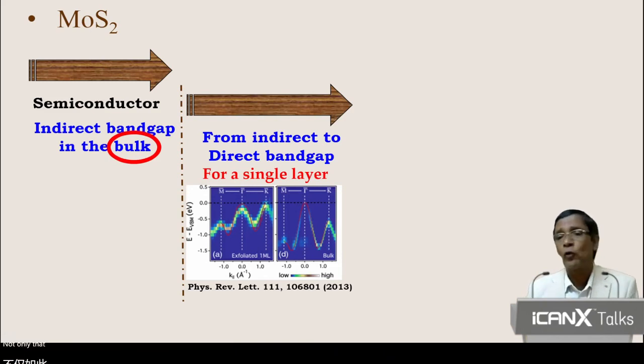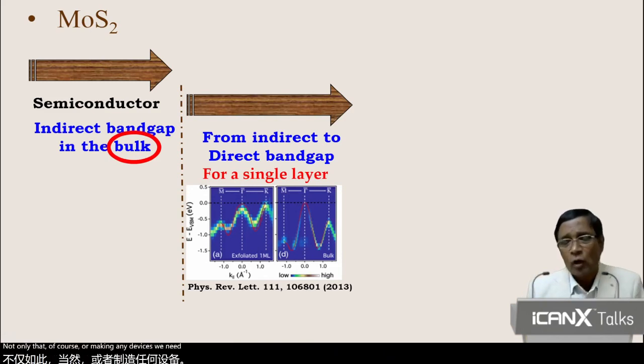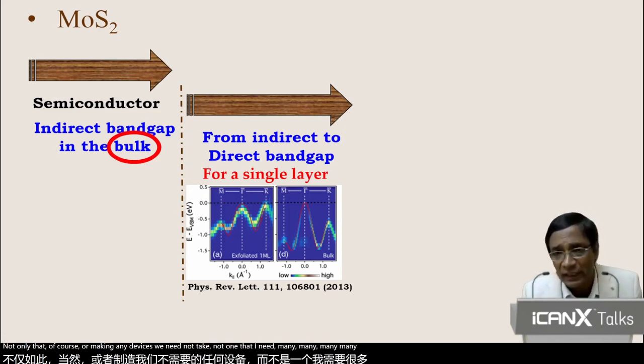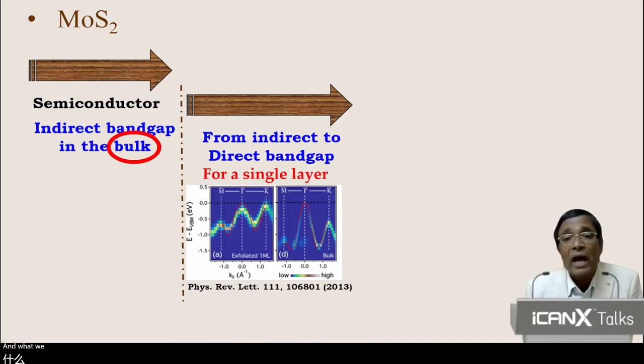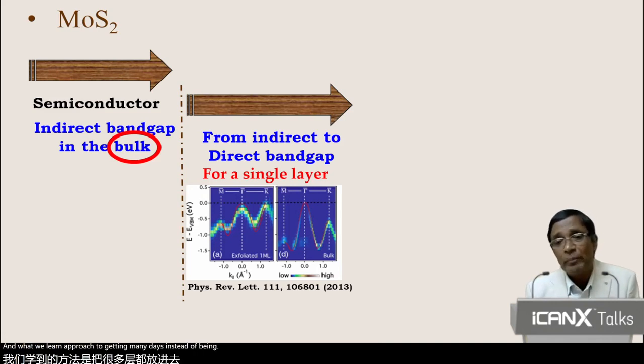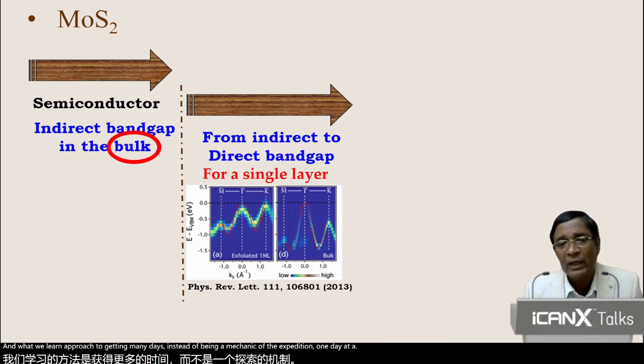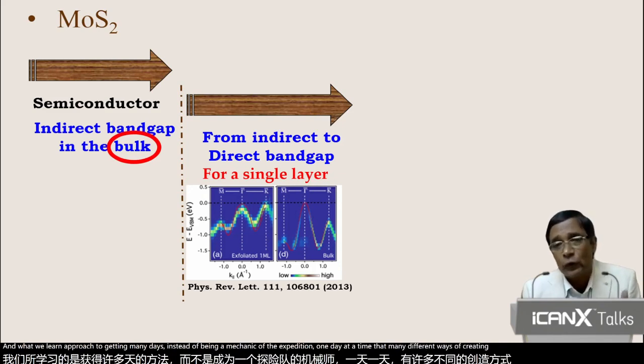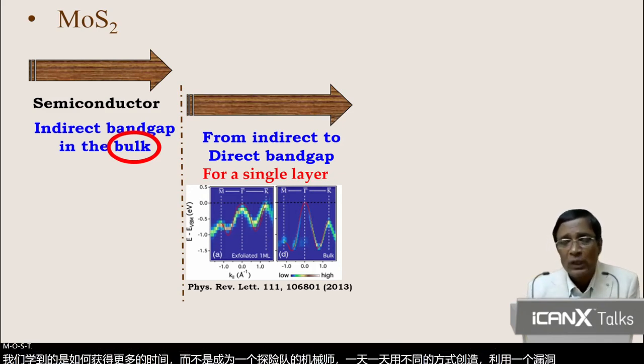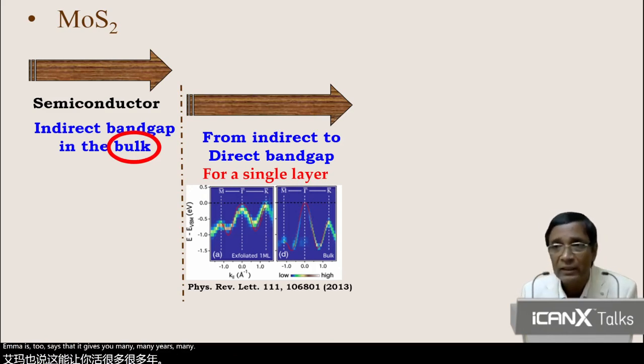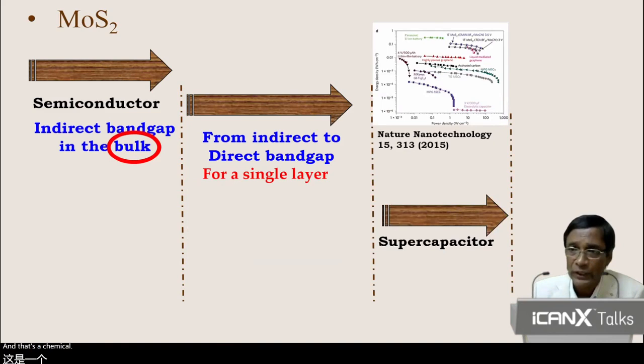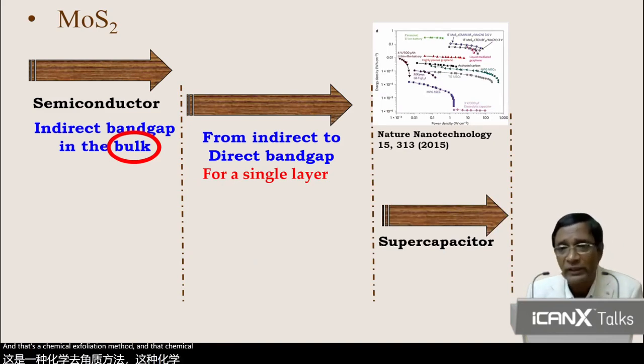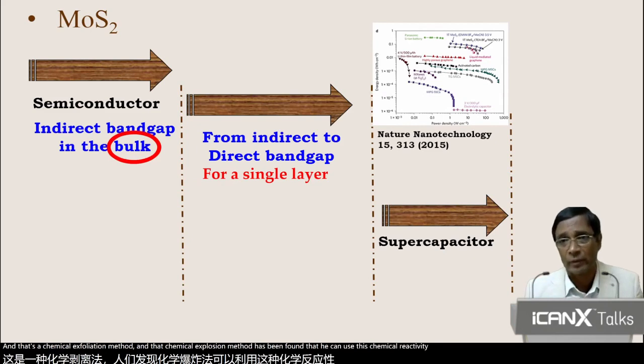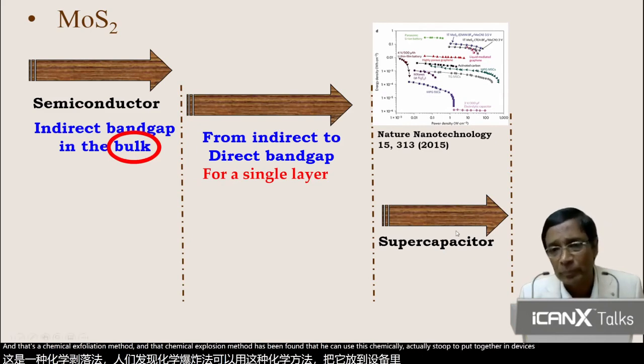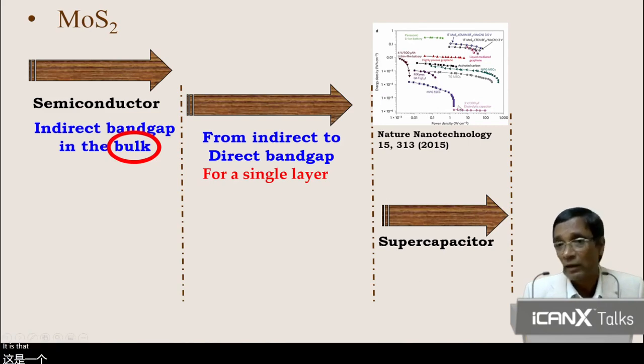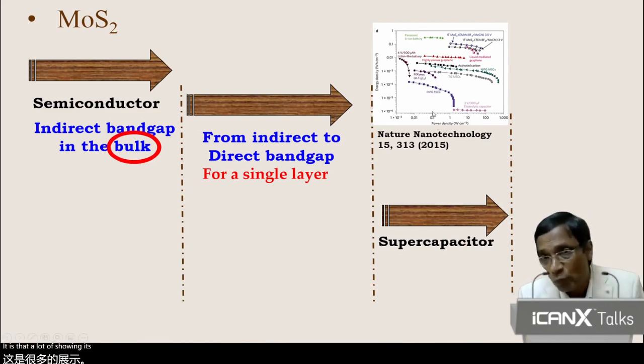Not only that, for making any devices, we need not one layer but many, many layers. And the popular approach to getting many layers, instead of doing a mechanical exfoliation one layer at a time, is that there are many different ways of exfoliating a bulk MoS2 such that it gives you many layered compound. That's a chemical exfoliation method. It has been found that you can use this chemically exfoliated MoS2 to put together devices, for example, a supercapacitor.